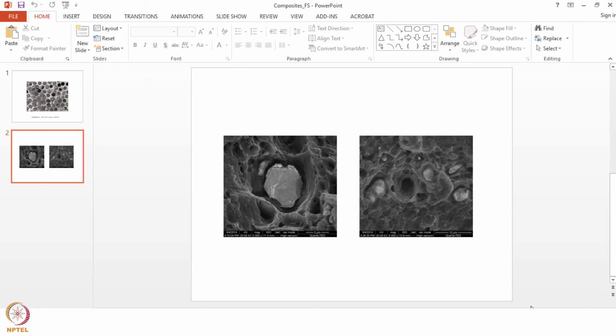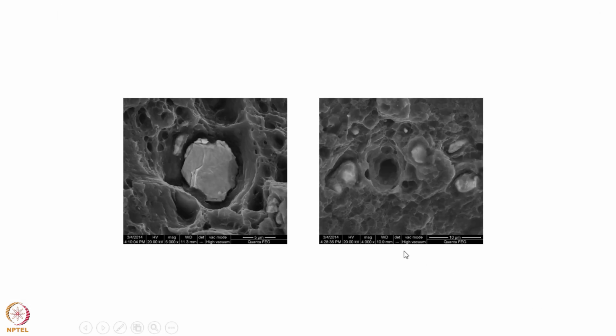If you do a careful observation of these two fracture surfaces over here, these are two micrographs captured in a scanning electron microscope. So here you can see a particle sitting inside a void, okay? So this is indicative of a good interface bonding, first of all, and this also tells you that the void nucleation mode is through particle fracture or particle cracking, right? So even after the fracture, the particle is still bonded to the matrix, as you could see, okay? So the particle has broken into two halves. Here you can see one half, and the other half can be seen in the corresponding part of the fracture surface. If you identify the same area on the other part of the fracture surface, you can see the other half of this particle on that part.